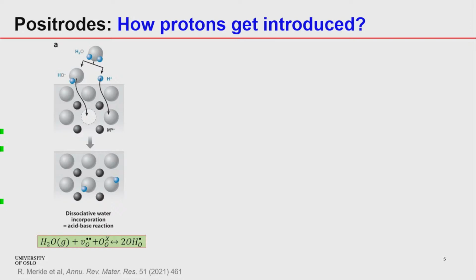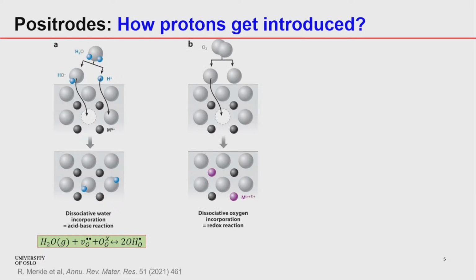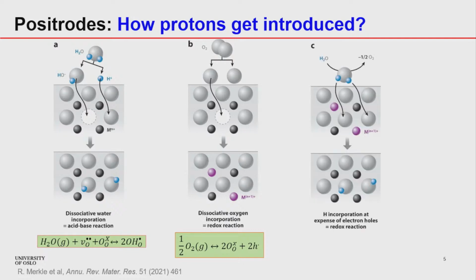The next reaction to see is dissociative oxygen incorporation, which is a redox reaction, where oxygen comes from the atmosphere, sits at the surface, dissociates, and the oxygen goes and sits at the empty vacant site. But because it needs some charge, it takes electrons from the transition metals such as cobalt and iron, and hence electrons are lost from there and we form holes, which can lead to electronic conductivity, which can be explained by this Kroger-Vink notation.